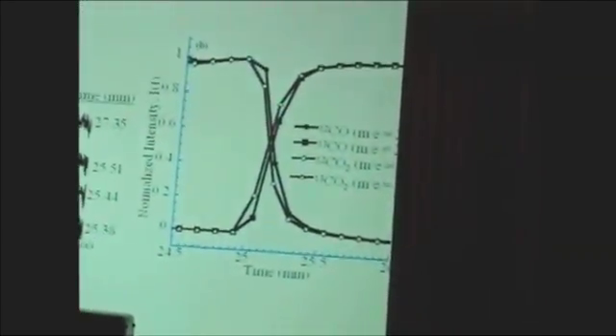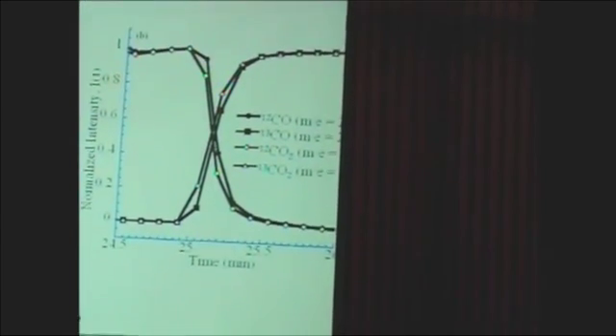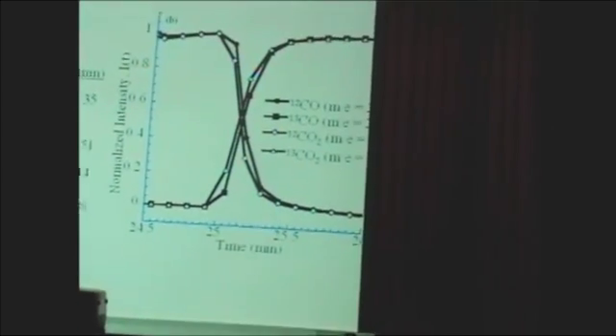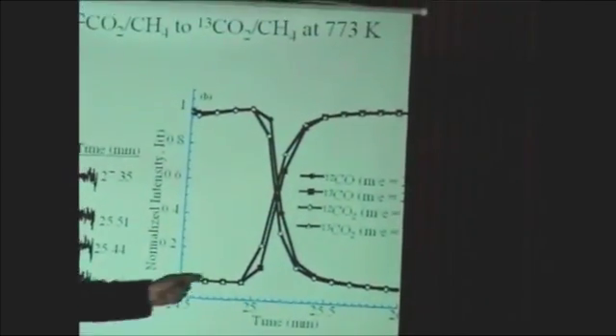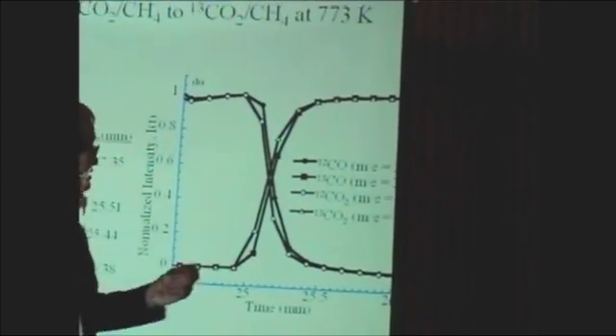So there's a lag here. There's a lag for the formation of 13CO. This lag gives you the indication that CO does adsorb on the catalyst surface. It takes time for conversion of this 13CO2 to CO. So this isotopic tracing technique can help us determine how long this adsorbed CO stays on the catalyst surface.